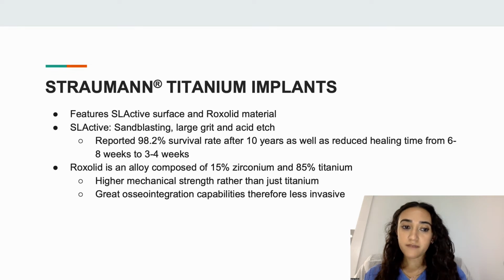It was reported to have a 98.2% survival rate after 10 years of inserting the implant. It also reduces the healing time of the implant from 6 to 8 weeks to 3 to 4 weeks. Roxolid is the alloy from which the implant is made. So instead of only titanium, it has 15% zirconium and 85% titanium. That alloy allows for higher mechanical strength rather than just titanium.